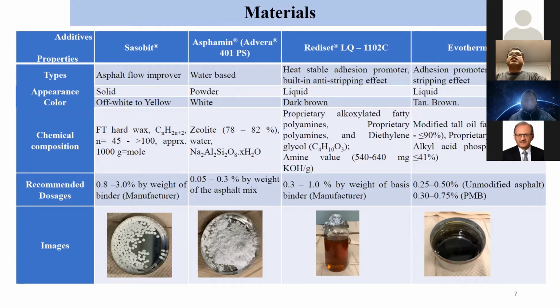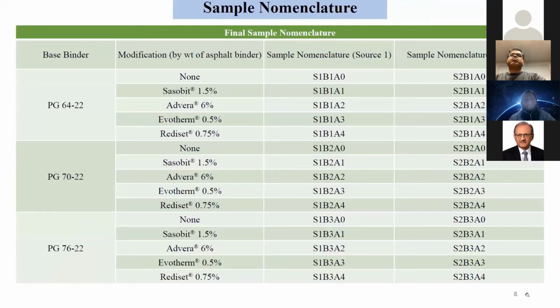As you can see, the scope was very expanded. So what we did, we did only the viscosity test, and from there and from literature, we determined what would be the optimum doses. And then we tried those optimum doses of each of the additives and looked into other properties. Next slide.